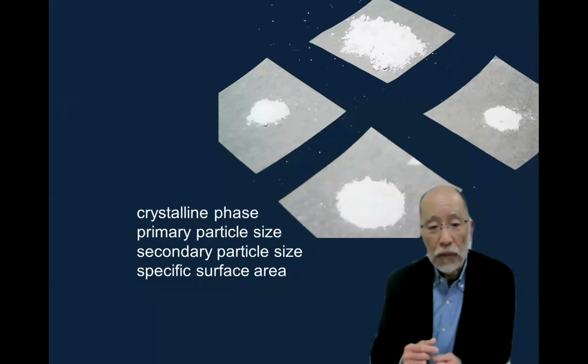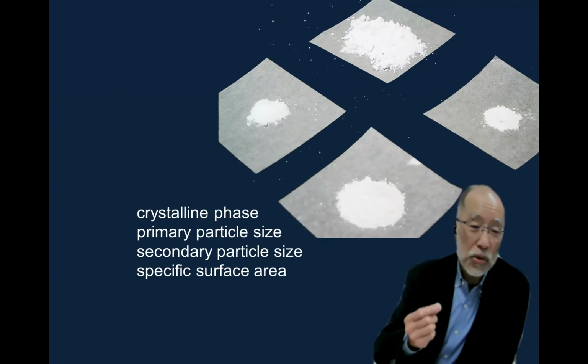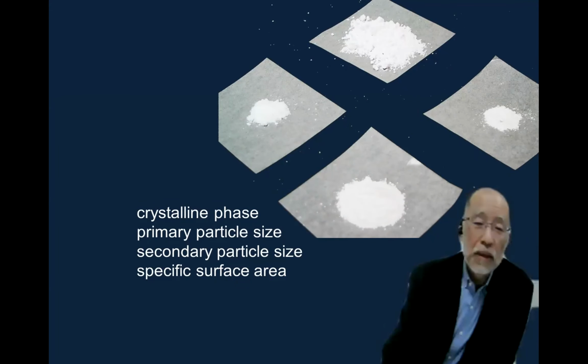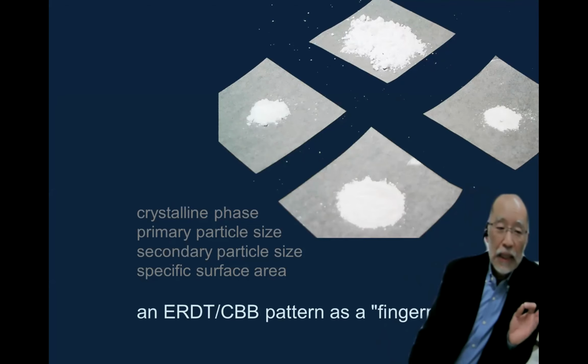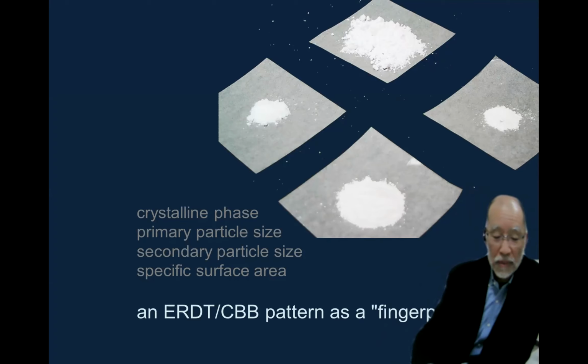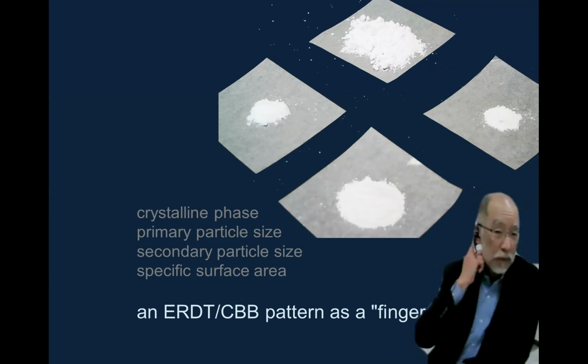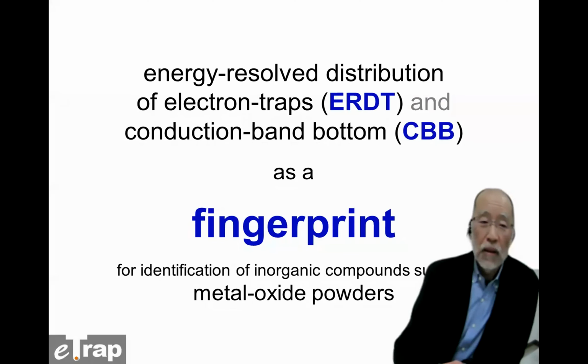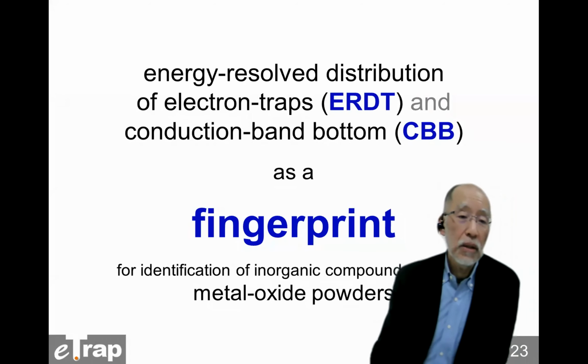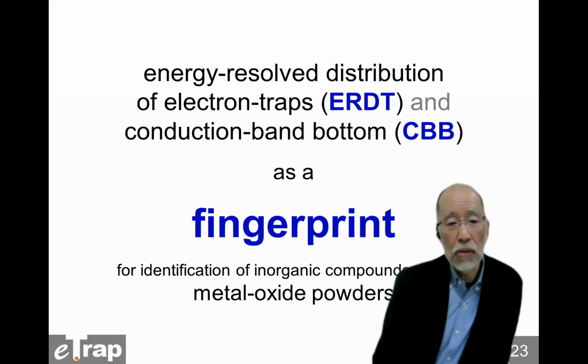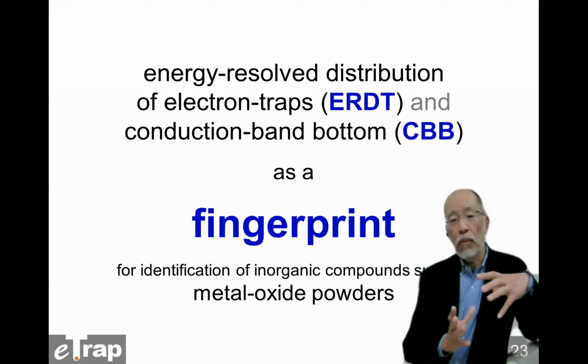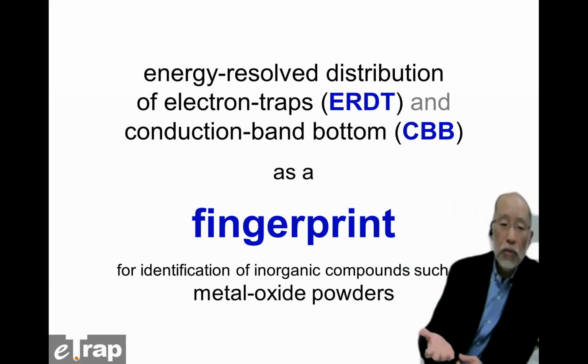So if we can obtain the fingerprint for inorganic solid compounds, it is possible to identify inorganic solids. And now I want to propose that the ERDT-CBB pattern can be used as a fingerprint of solid inorganic materials. Without using other conventional analytical data, I think it is possible to identify solid compounds by using the ERDT-CBB pattern. And what is the ERDT-CBB pattern? ERDT is energy-resolved distribution of electron traps, and CBB is the conduction band bottom. Those combined patterns can be used as a fingerprint for identification of inorganic compounds, such as metal oxide powders.